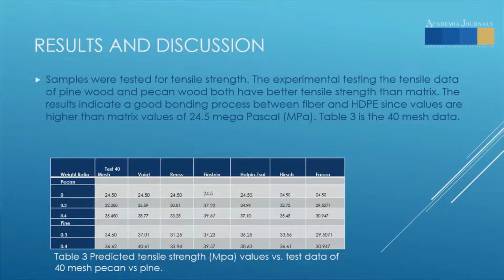The results that we obtained for both materials were better than the matrix. The HDPE has 24.5 megapascals as ultimate tensile strength. Our table for 40 mesh shows that both materials have a better response at 30 and 40%.